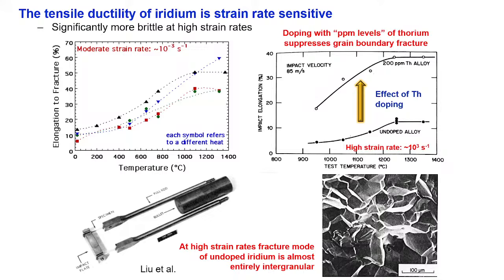But if you dope with a small amount of thorium, about 200 ppm, it shifts the ductile-brittle transition dramatically. So all of a sudden, and these were experiments done in an impact gun where we fire a bullet, and we can do experiments in tension at strain rates of 10 to the 3 per second. Without the thorium, you get mostly grain boundary fracture, and with the thorium, you get transgranular fracture.